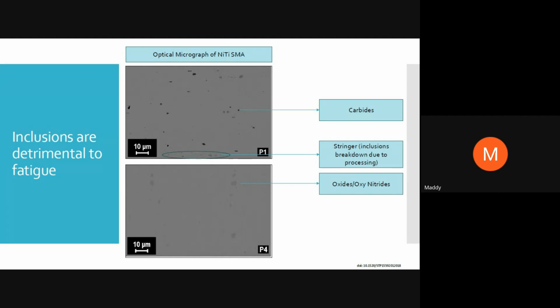So I just mentioned inclusions. Inclusions are very bad. And when it comes to nitinol, there are predominantly two families of inclusion. One is the carbide, and the other one is the oxide or oxynitride. For carbides, the chemistry is typically TiC, titanium carbide. It is a titanium carbide inclusion, and it usually appears like a black particle, like what you see in this image. These are all optical images. You can see the scale, 10 microns. Those are your carbide inclusions, the ones that appear in the black contrast. The lighter one, the light gray, is actually the oxide or the oxynitride.